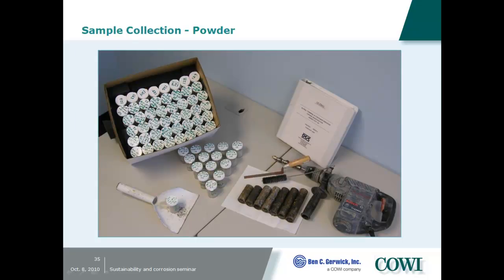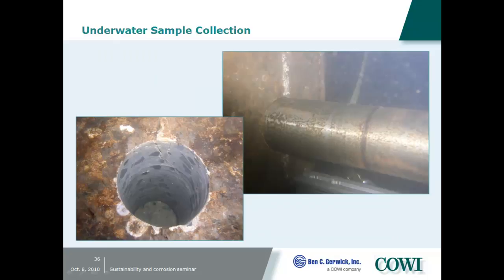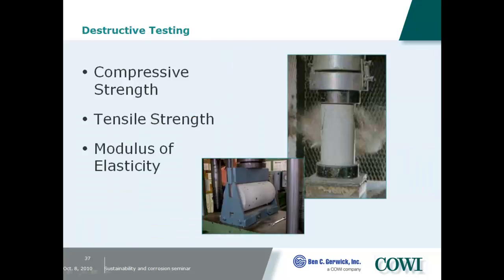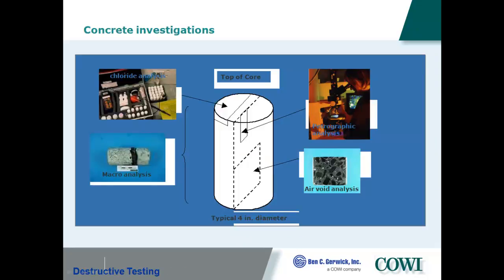And you can take diamond drills and take out dust samples, which you can do a lot of compared to the time you use for coring. But the accuracy on dust samples is so much smaller. If it's chloride analysis, we're talking plus minus 40%. Underwater, don't forget the areas where you cannot easily see how the condition is. Often it will be compressive strength testing. And the good thing about cores is that you can combine different test methods and get results in combination.